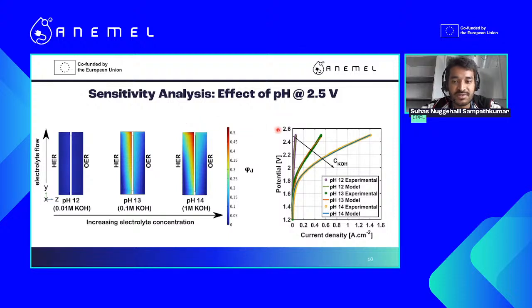As an effect of pH as well, we fixed a certain voltage, which was 2.5 volt, to see how the pH, or basically the amount of potassium hydroxide salt in the water, affects the performance. It basically shows that the more potassium hydroxide you have in the water, the more hydrogen gas is evolving, because this directly translates to increasing current density. It was not really much of a surprise, but it was a good thing to map and identify, for these material combinations, what could be the potential range of operation of the electrolyzer.